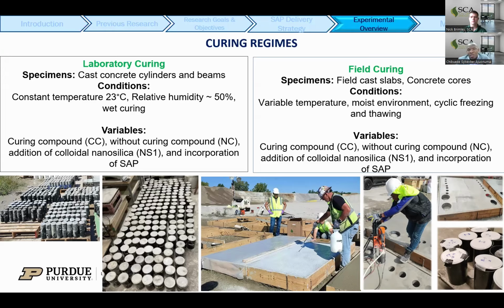And then also we had some that were cured in the field. They were concrete slabs cast in the field, and they were left there for a period of 365 days. And for them, the condition there was a varying temperature, there was moist condition, and cyclic freezing and thawing. And then also we had those with the curing compound and those without the curing compound.